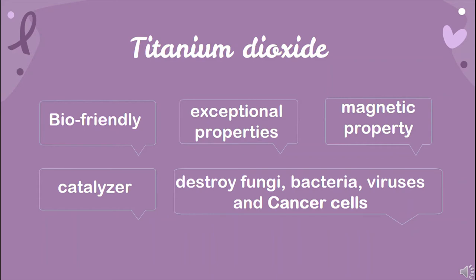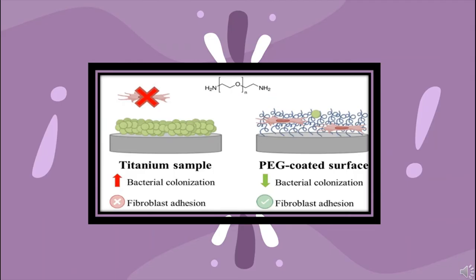Titanium dioxide nanoparticles have been used in biomedical applications such as PTT, drug delivery, cell imaging, biosensors for biological assays, and genetic engineering. In aqueous media, titanium dioxide nanoparticles tend to aggregate, which can cause problems in biological systems. The surface of these nanoparticles should be modified to prevent aggregation. Covering nanoparticles with hydrophilic polymers is one of the most common ways to prevent aggregation, and polyethylene glycol is one of the best polymers for this purpose. The biocompatibility of nanoparticles is improved by attaching polyethylene glycol to their surface.